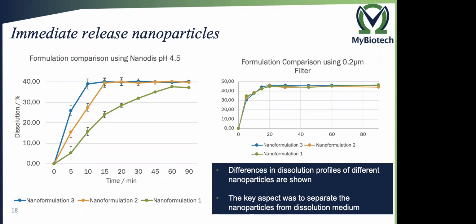Then we have done a dissolution comparison using this method, where we prepared three different nanoparticles. The idea was we wanted to see the differences between these three different nanoparticles. On the left side, you can see we have formulations 1, 2, and 3. Formulation 3 has the highest dissolution profile and 1 has the lowest dissolution profile, the green curve. The reason for that is the blue one has the smallest particle size, and the green one has the biggest particle size. So we could see the expected results, that we can change the dissolution profile of a nanoparticle formulation using only the differences in the particle size.